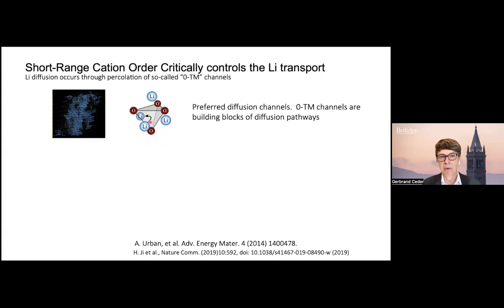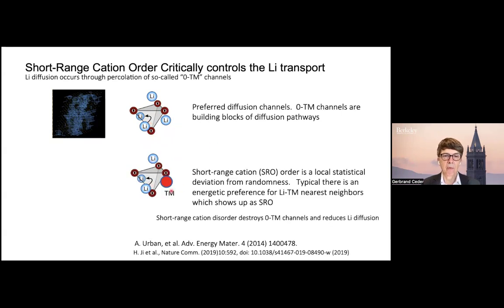But actually, in most cathode materials, because of electrostatics, there is a preference when you have a lot of lithium to bring a transition metal nearby, because that gives you a local charge balance. And what you see is if we get this one TM channel instead of this zero TM channel, we will be destroying a diffusion path.